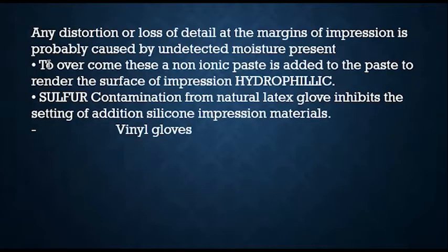So any distortion or loss of detail at the margins of impression is probably caused by undetected moisture that is present in the oral cavity. So to overcome this, a non-ionic paste is added to make the impression hydrophilic. And another disadvantage is sulfur contamination from natural latex glove that inhibits the setting of addition silicone. Only vinyl gloves are recommended while you make an addition silicone impression material.